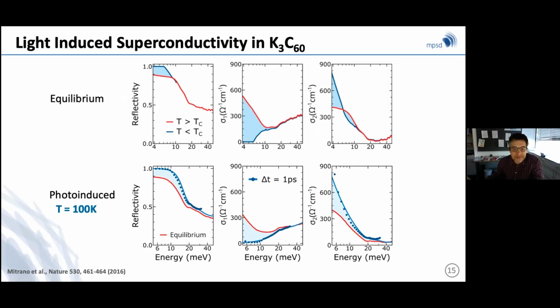So some form of stimulated condensation, and secondly, an excitation gap that appears to be larger than the equilibrium gap. And whether this is really a superconducting gap or the beginning of a polaronic peak is not 100% clear. But nevertheless, qualitatively, one can at least say that this is a superconducting-like optical spectrum, in as much as it has a gap and it has a very high conductivity, as shown by these features.